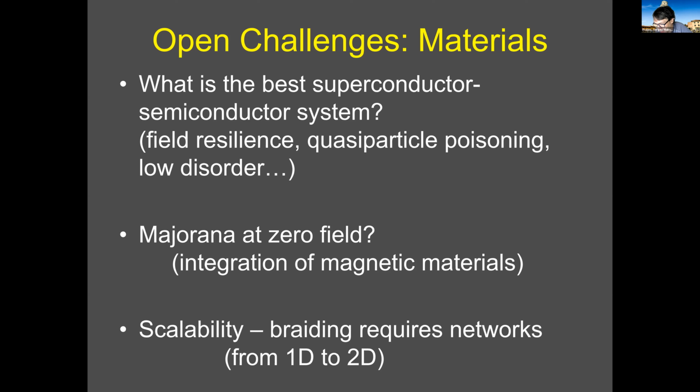Okay, is there understanding why one gets quantum dots in these wires? I answered partially this question, right? So part of it is disorder, you know, surface during fabrication. But another part is just geometry, right? It's a complicated device. To measure two Majoranas, you have to put contacts on top, gates underneath. Contacts could be asymmetric. So just the geometry of the device can create confinement that we don't want. We don't think it's in our Hamiltonian, but it is.